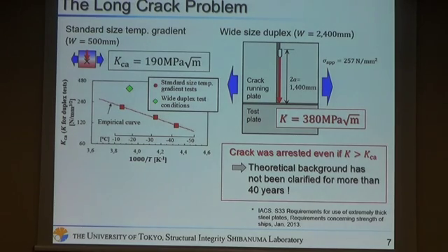However, in the wide size duplex test, it has been reported that the crack was arrested even if stress intensity factor is larger than arrest toughness KCA. This theoretical background has not been clarified for more than 40 years. That is a long crack problem.